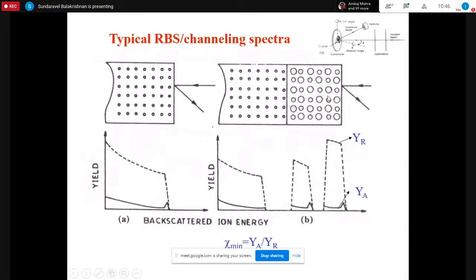Suppose there are two different elements in the top layer grown on the substrate. In RBS you know that ions scattering from heavier atoms will come at higher energy, and ions getting scattered from lighter atoms will come at lower energy. A much lighter atom will come at much lower energy. And once we align the beam, there is a drastic reduction in scattering signal from all the elements, from the top layer as well as the bottom substrate layer.